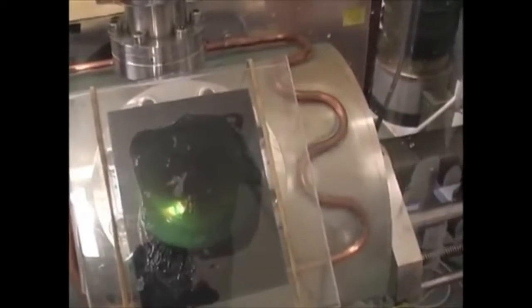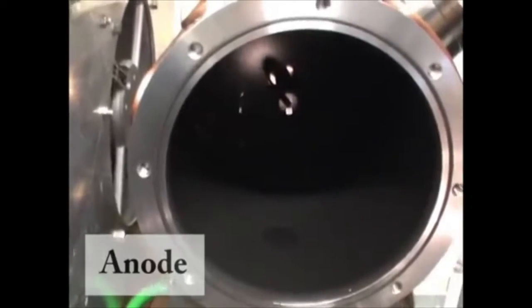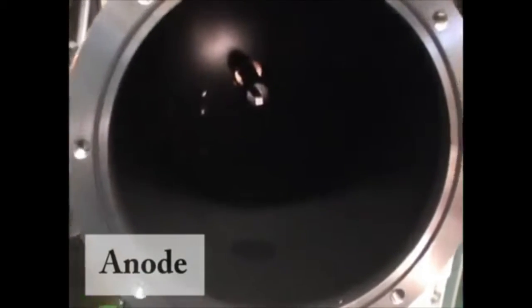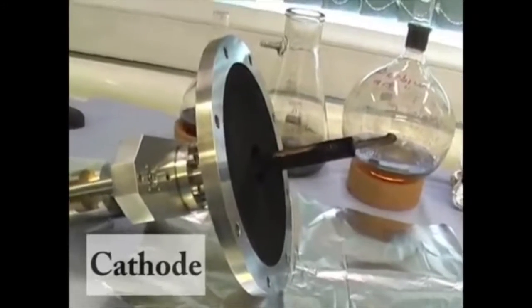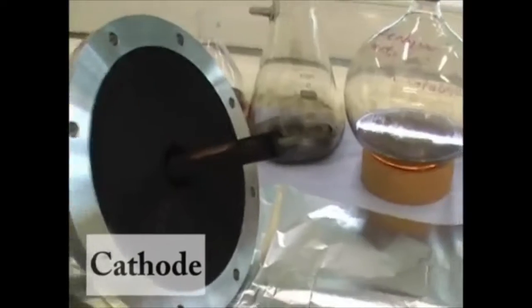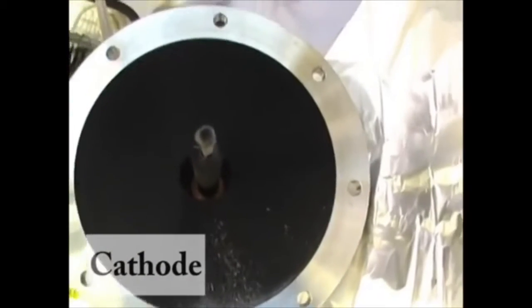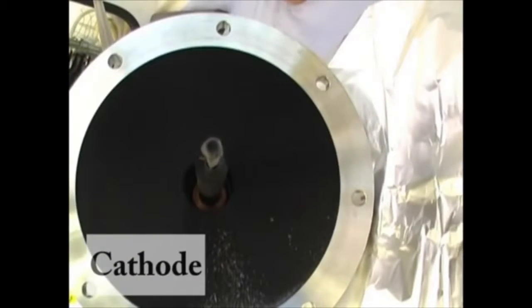Black soot is produced and starts to cover the whole chamber, including the window, so after a while we can't see anything anymore. When we open the chamber, we can see how the anode is being consumed, and the black powder is deposited everywhere around. On the cathode there is also black powder, where we will find carbon nanotubes, normally with 20 to 30 walls, although if we also include a metal catalyst in the anode, we can obtain single-walled nanotubes.